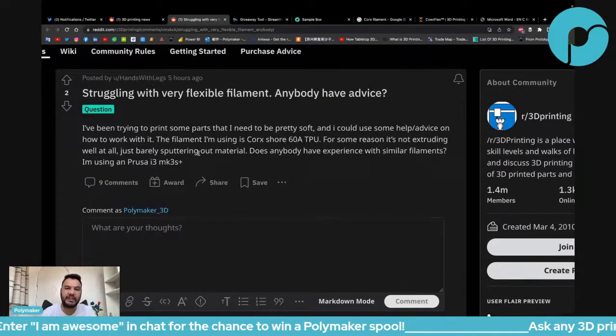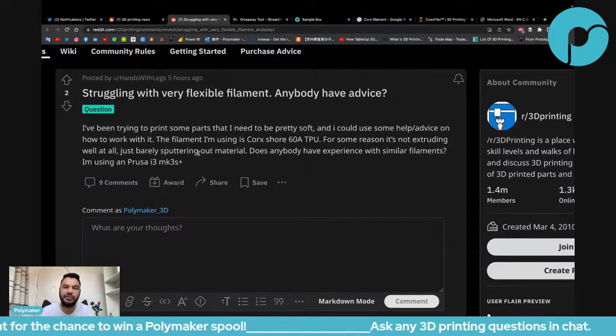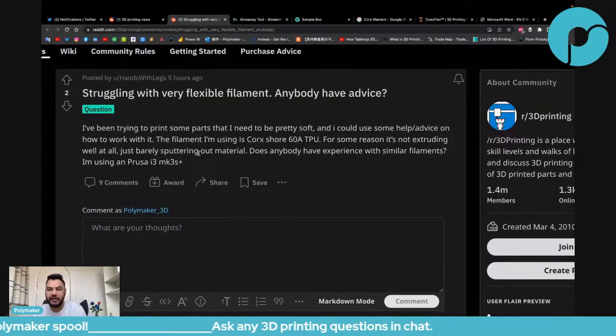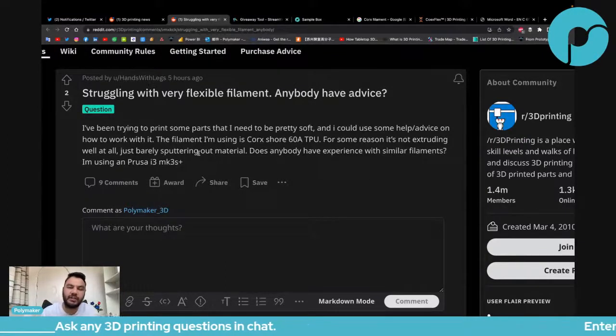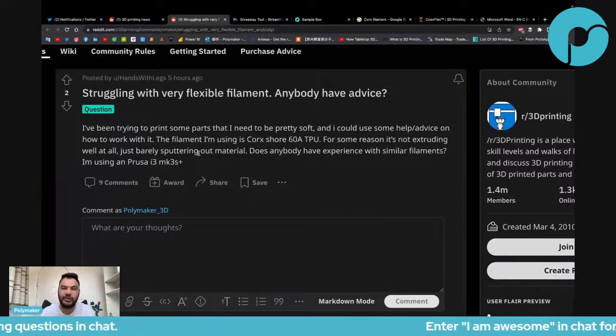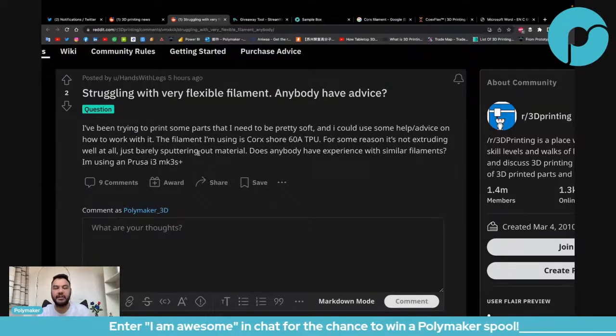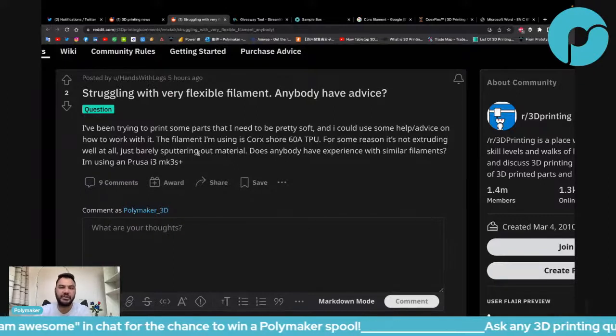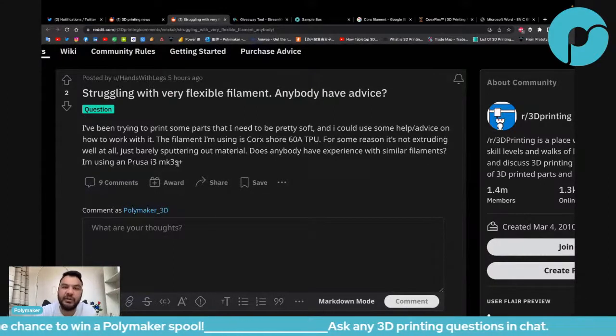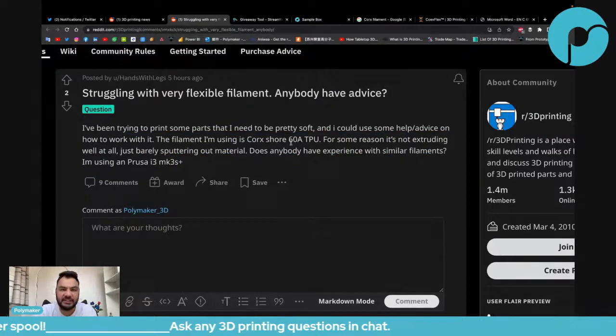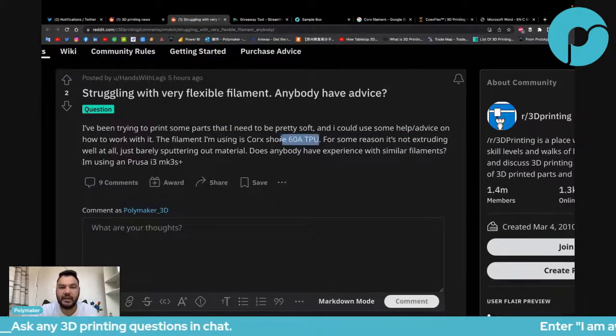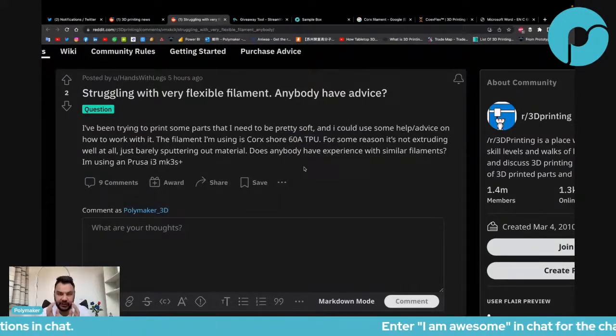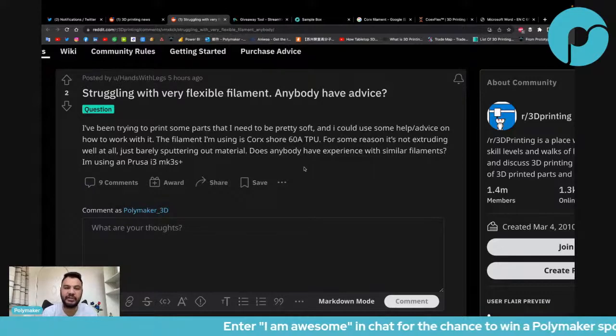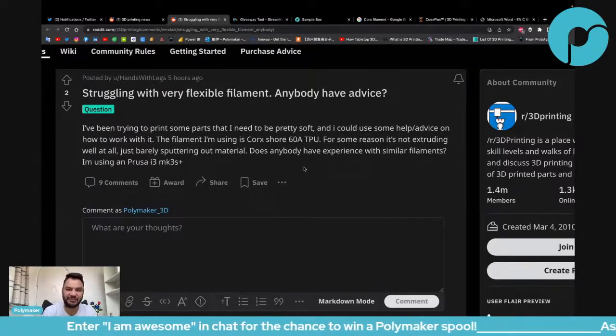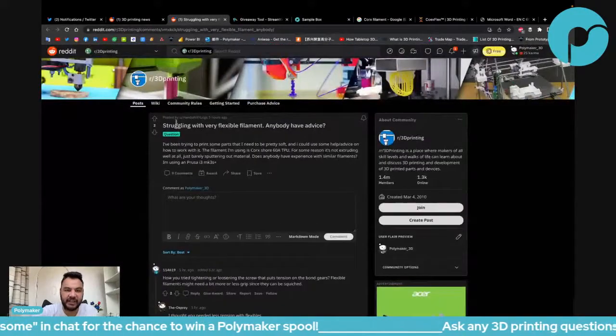So that's one way. The second way is you have to lower the needed pressure for the extrusion. The needed pressure comes from the viscosity of the material. The higher the viscosity, the more pressure you will require to extrude, and the lower the viscosity, the less pressure. And how to lower the viscosity? You have to increase the printing temperature. But in this case, you cannot go above 230. So that means this material is basically very, very challenging to print. Either you really need a very, very good hot end to print that material, or you print it at, I don't know, 2 millimeters per second or something like this. But that's my take on this.